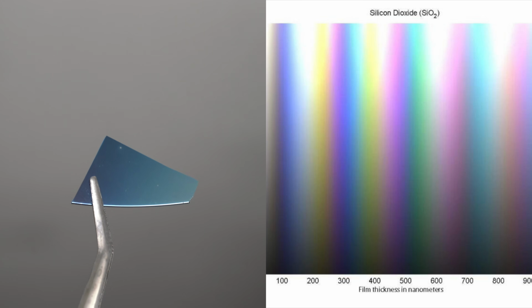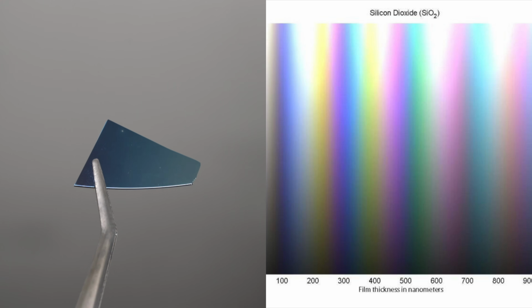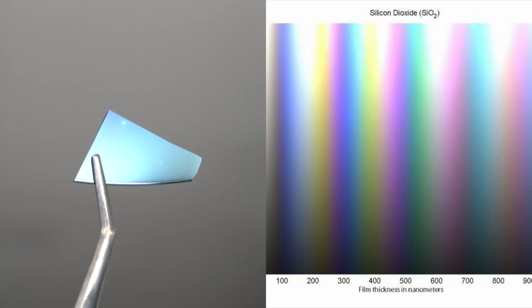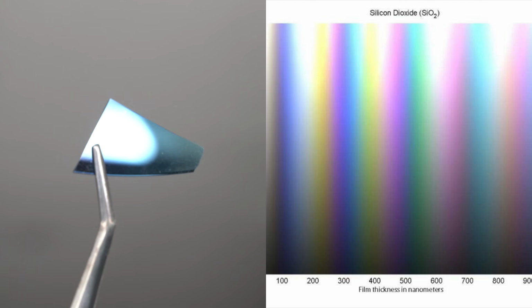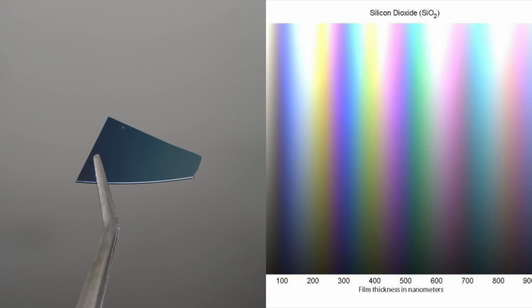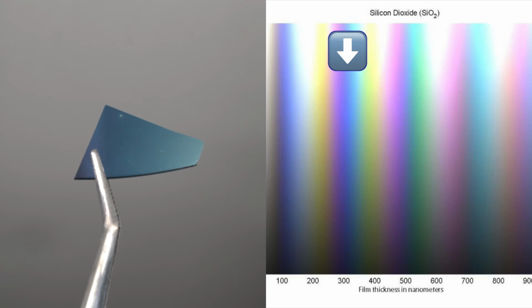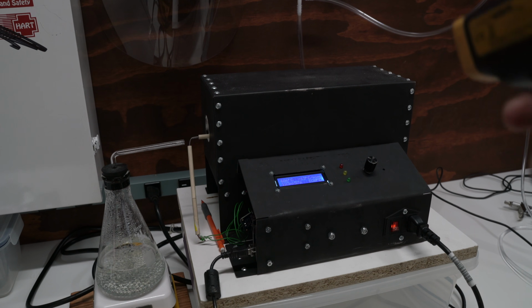The thickness of the oxide layer and the color you see are directly related, so you can actually use this to determine what thickness we have. This blue color corresponds to about 320 nanometers or so. Well, that was a great success.